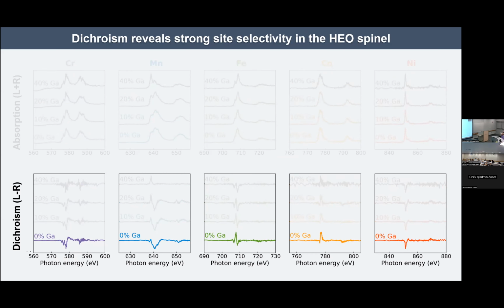One of the first things that we can see, if we just look at the dichroism for only the 0% gallium sample, is that some elements show a predominantly negative dichroism, whereas some elements show a predominantly positive dichroism signal. And this is exactly correlated with our ferrimagnetic order. We have these 2 anti-parallel sublattices. So when I apply a magnetic field, the larger moment sublattice, the octahedral sublattice, is going to align with that field, and the anti-parallel sublattice on the tetrahedral sites is going to anti-align.